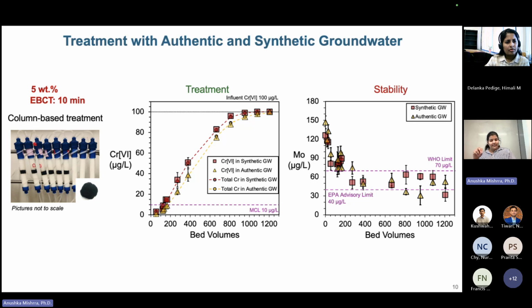Anyway, we tracked this molybdenum that was being released, and what we saw is that while the material is removing chromium-6, it is releasing molybdenum in the water. That is concerning because we don't want people to drink molybdenum in place of chromium and have different health effects. We could see that this is happening at groundwater pH conditions.